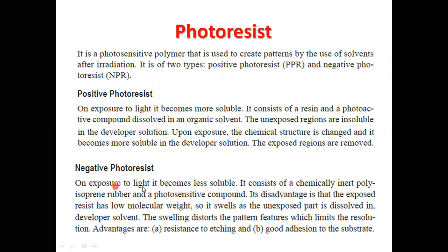On exposure to light, it becomes less soluble. It consists of a chemically inert polyisoprene rubber and a photosensitive compound. Its disadvantage is that the exposed resist has low molecular weight, so it swells as the unexposed part is dissolved in the developer solvent. The swelling distorts the pattern features, which limits the resolution.